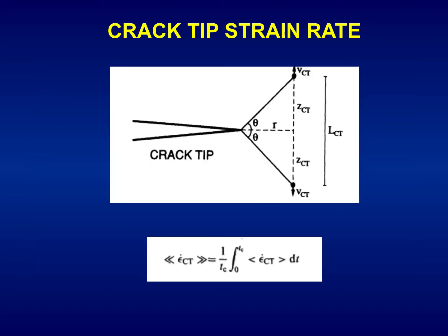According to this schematic, we compute the crack tip strain rate as a time and space average of the local strain rate at the crack tip. This instantaneous value of the crack tip strain rate is averaged over time from 0 to the critical time to failure during the test, and in addition, it is averaged over the critical distance. Then we use the critical distance concept, CDC, or the concept of zone affected by hydrogen. In the case of pearlitic steel, it is the so-called tearing topography surface, TTS zone.